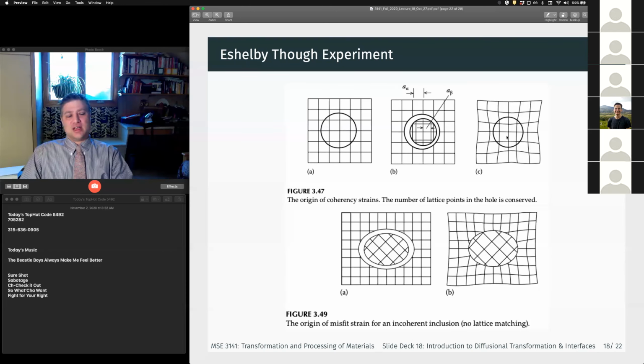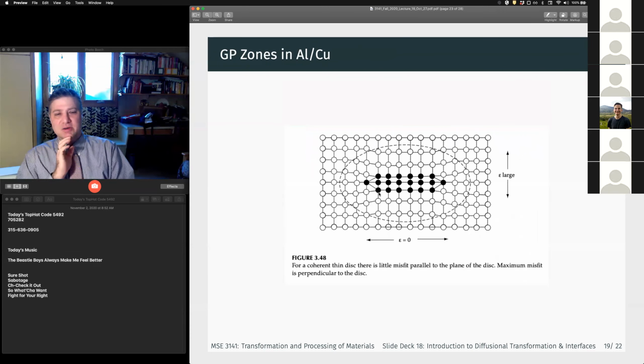Some directions in a crystal are easier to pull on than others. They're not as stiff. Our Young's modulus has a directional dependence in a crystal, right? So we need to take that into account as well. And one of the most well-known examples of this is aluminum copper, right? In aluminum copper, the equilibrium theta phase is a very large unit cell with a fully incoherent interface, and it's very, very difficult to nucleate.